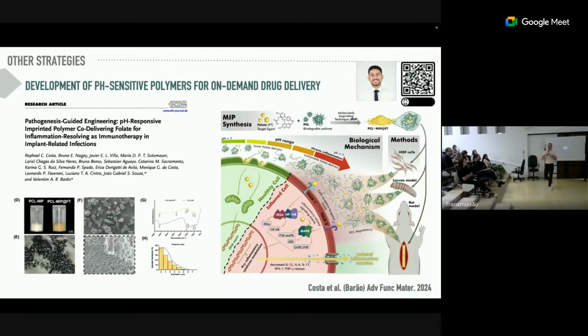We have also developed other strategies, like in this study from my previous PhD student. We developed here a molecular imprint polymer that can deliver folate. Folate has been used in the past quite a lot for periodontitis, because it can control the inflammation. People normally administer that systemically, but in this case, we tried to develop something that can be released locally and controlled by the pH. I'm not showing the data here, just the image, but we were able to show for the first time that inflamed fibroblasts have a receptor, FOLR1 and FOLR2, for this folate, and this folate can penetrate into the cell